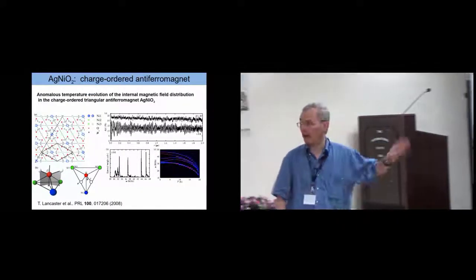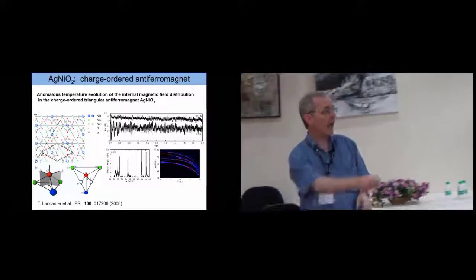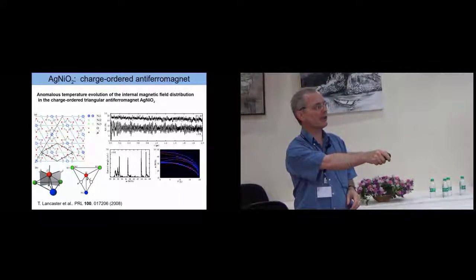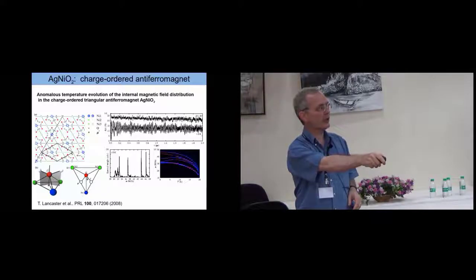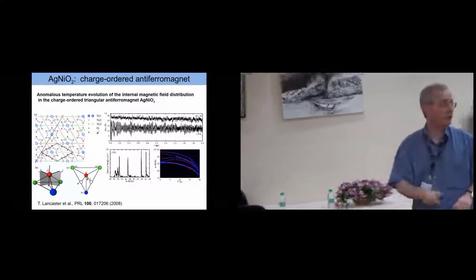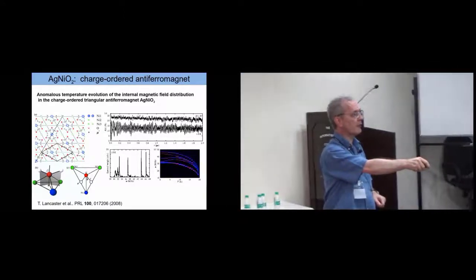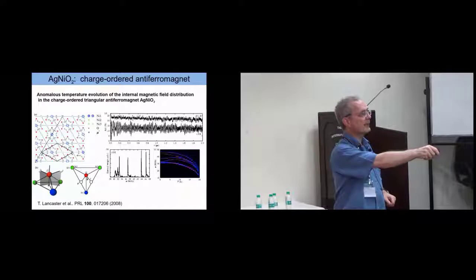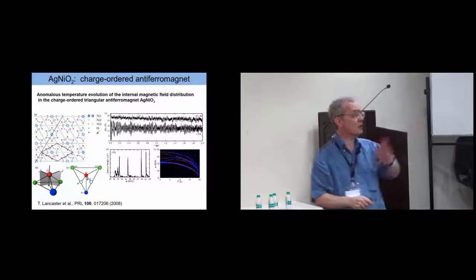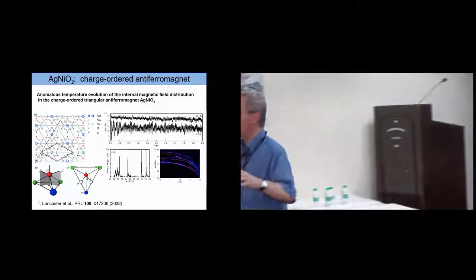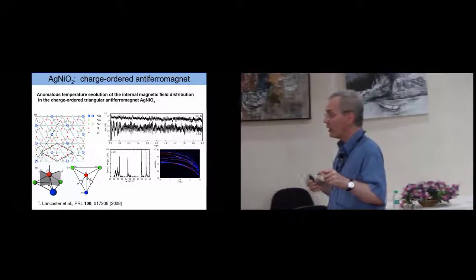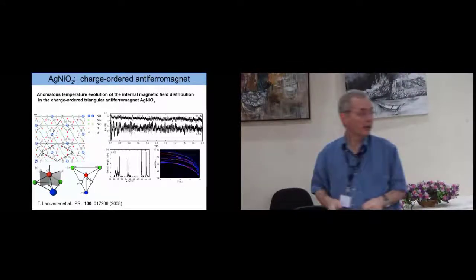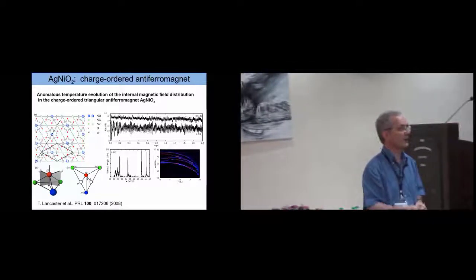Here is another example. Both of these examples are from PSI, actually. I wanted to show this because when we first measured it, it looked like noise. This is down at 1.6 Kelvin. The spin relaxation is up here at 20 Kelvin. And here you can just see something very, very complicated. But if you Fourier transform it, you see six frequencies. So we were able to fit these oscillations with six individual frequencies. And there are so many here because this is a charge-ordered material that shows a rather complicated magnetic structure, and we were able to understand this very nicely using the muon data.